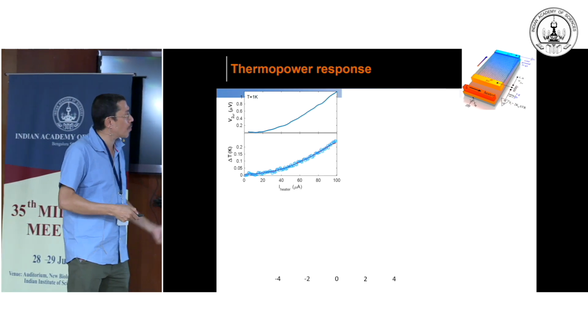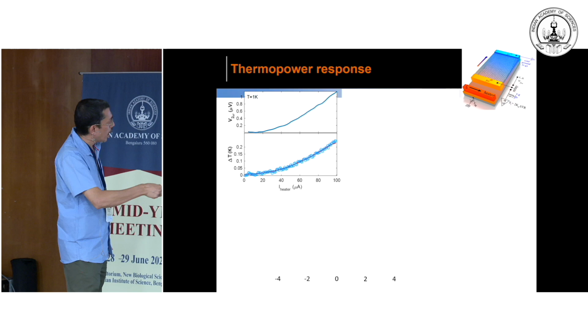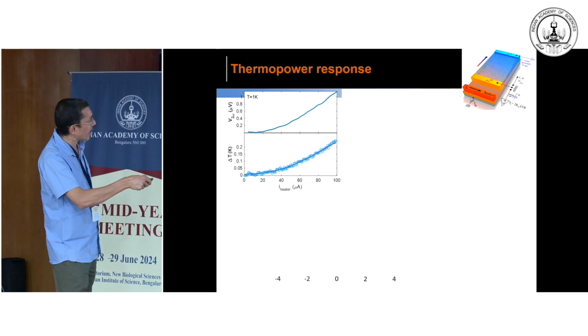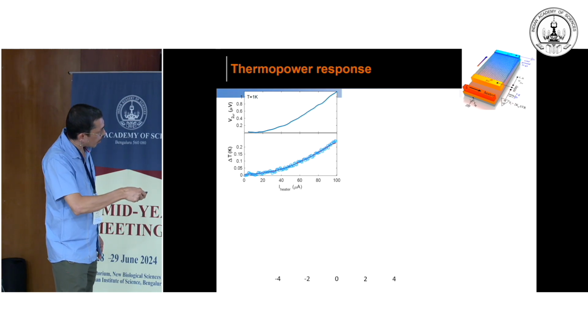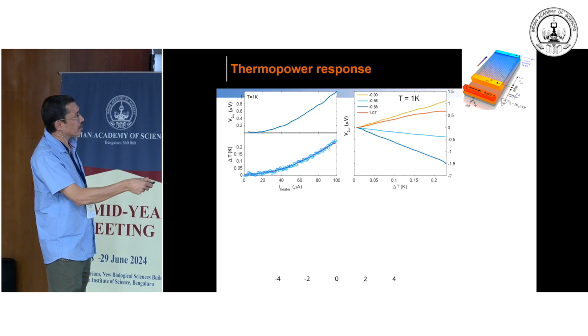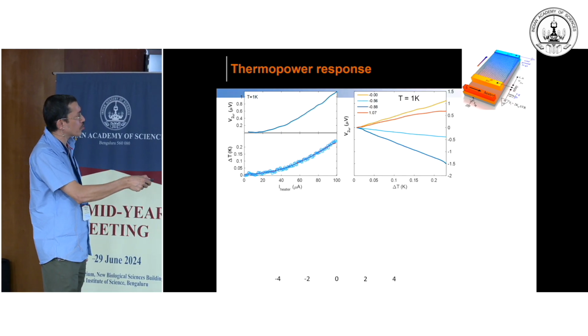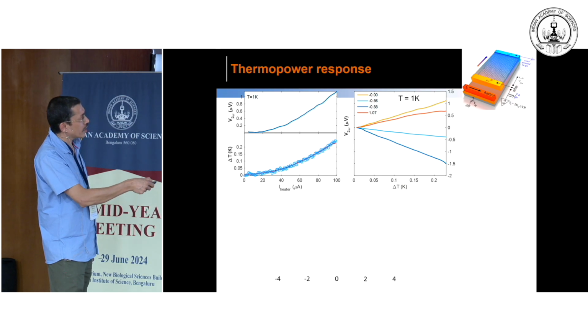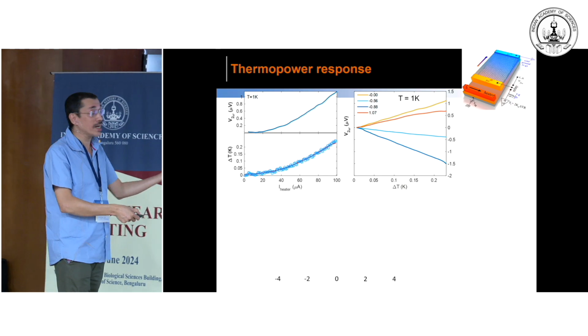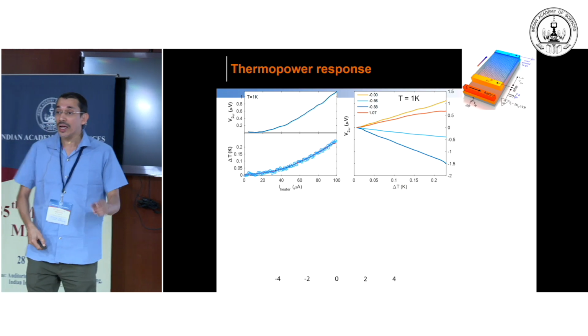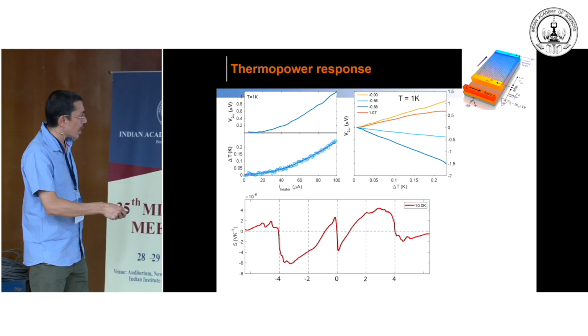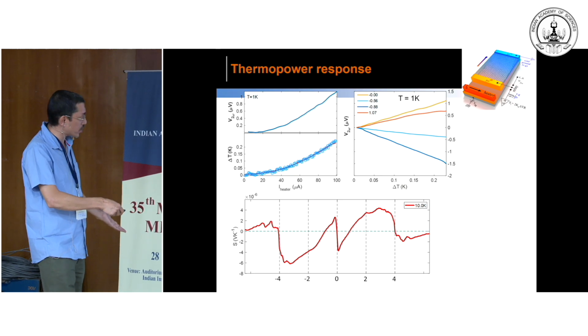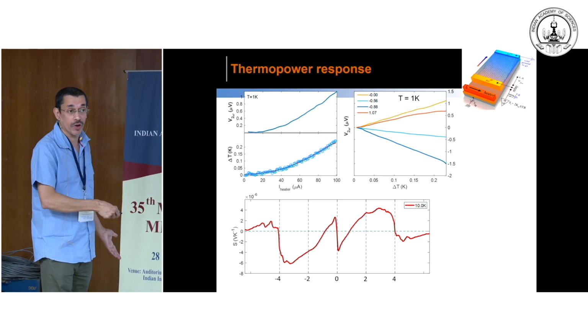We measure this temperature gradient by noise thermometry, and this is the noise thermometry data as a function of heater current. You are passing a current, it creates the thermoelectric voltage, and you are measuring both of them simultaneously, the voltage as well as the temperature. If you plot them together, for different gate voltages, you see that V2 omega and delta T are increasing linearly. That tells you that you are in a linear regime, and the slope of this data gives you the Seebeck coefficient. This is your thermopower or Seebeck coefficient as a function of carrier concentration of your twisted bilayer graphene.